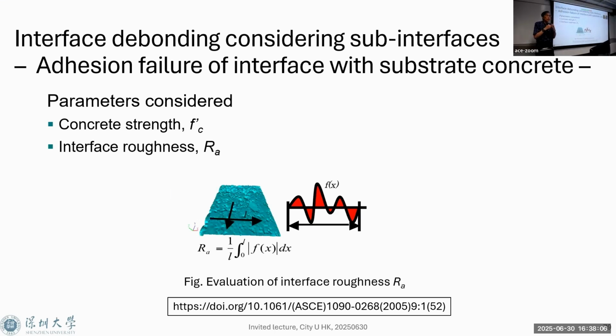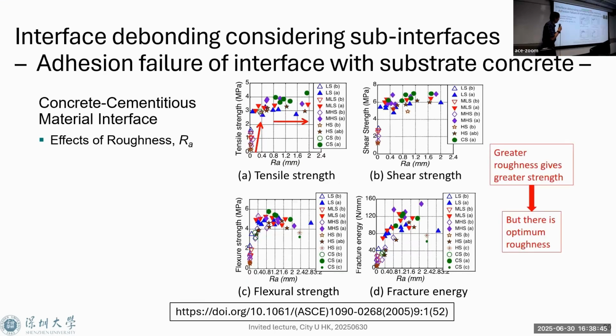So in this case, the debonding takes place clearly at the interface between two materials. In this case, concrete strength and interface roughness are the main factors. In the previous case, the debonding takes place within the substrate concrete, so roughness doesn't matter. But at the real interface, roughness does matter. So this is the experimental result. As roughness increases, the bonding strength increases. But once roughness reaches a certain amount, about 0.5 millimeter, the bonding strength becomes constant.